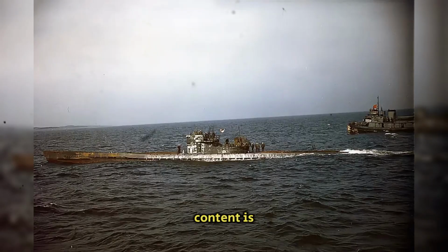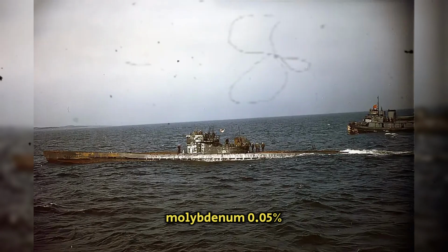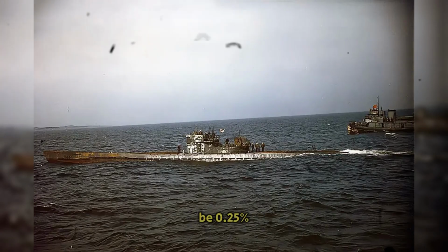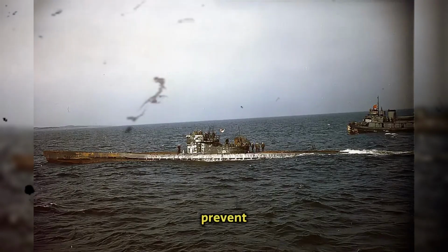The carbon content is slightly too high, enough to make the metal hard but brittle. Manganese is lower than normal. Silicon is within range, but one number leaps off the chart. Molybdenum, 0.05%. It should be 0.25%, 5 times less than specification. Whitmore freezes. He knows immediately what this means. Molybdenum is rare, one of the few alloying elements that prevents steel from shattering under stress.